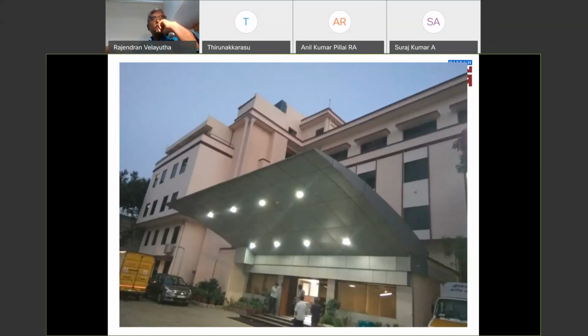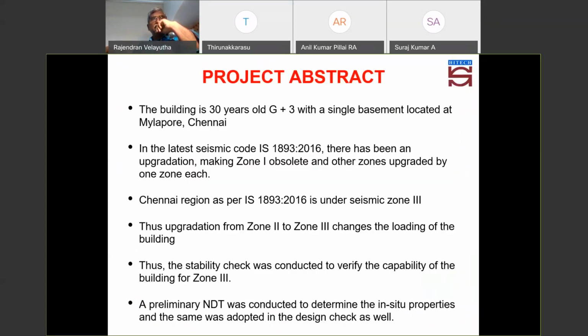Very recently, we have done one such building in Mylapore, a 30-year-old building with a basement and 3 floors. On account of the zone 3 conversion, they wanted to go ahead with the zone 2 to zone 3 conversion, and we did the usual simple NDT tests. For converting from zone 2 to zone 3, what we want is the fck value of the concrete, and we need to do a profometer survey to get the reinforcement detailing, as they didn't have the reinforcement detailing of this particular structure.